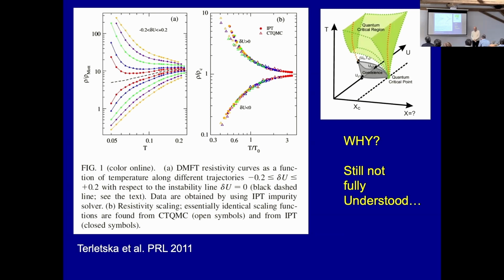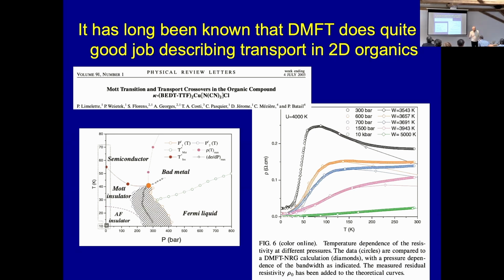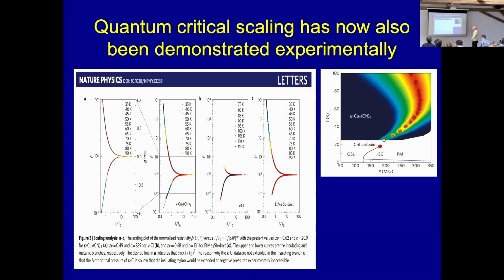But being there in the theory, this was again put to the test in actual experiments. It's been known for already a couple of decades that if you look at transport on a global scale, the dynamical mean field theory does a pretty good job at describing resistivity versus temperature for the kappa organics. This is an early paper we wrote with Patrice Limelette and my former student Serge Florens on this topic. But in recent years, this was pushed much further. And this is a paper, again, from Kanoda's group, in which they tested, now at much higher T, in the 40 to 100 Kelvin range, accumulating a whole set of conductivity data. They were able, in different materials, to scale the conductivity data, but this time using this quantum critical scaling.